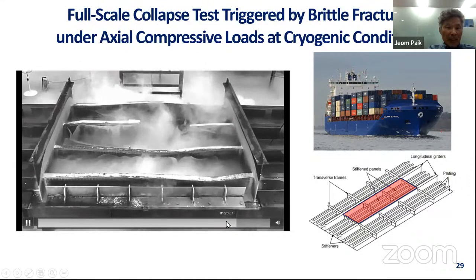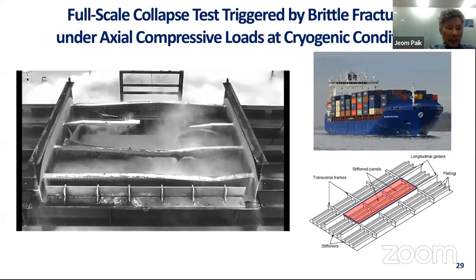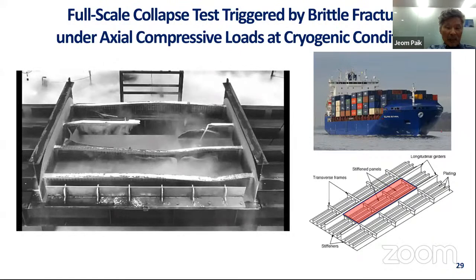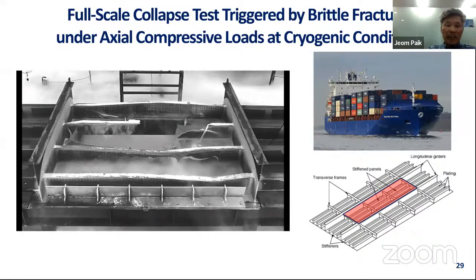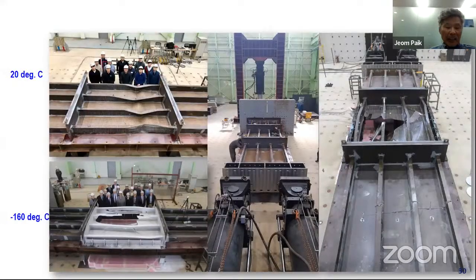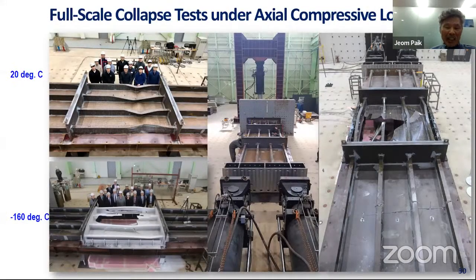As you can see from the testing, steel structures reached ultimate limit states triggered by brittle fracture. On the other hand, at the room temperature of 20 degrees Celsius, the same structure reaches ultimate limit states by the usual tripping of stiffeners under axial compressive loading. These tests obviously tell that brittle fracture can be a critical failure mode for steel structures at cryogenic conditions.